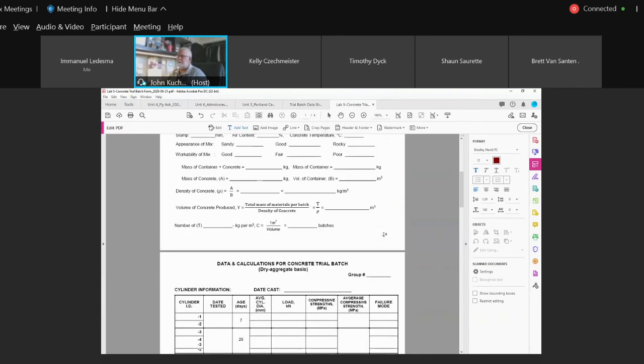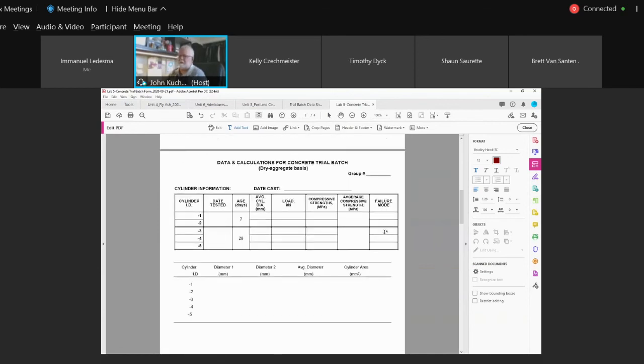If you scroll down to the next page, I had modified it. As time went on, we decided to test more concrete. So here, we tested 2 cylinders at 7-day and 3 at 28. So when you were batching concrete, you made a set of 5 cylinders. So 2 were tested at 7-day, 3 of the cylinders were tested at 28. The date cast is all the same because you made them all at the same time.